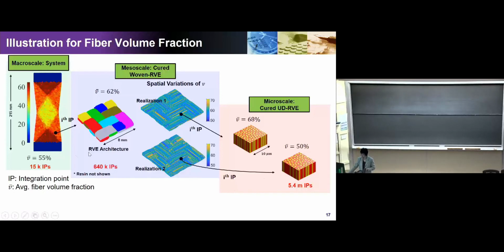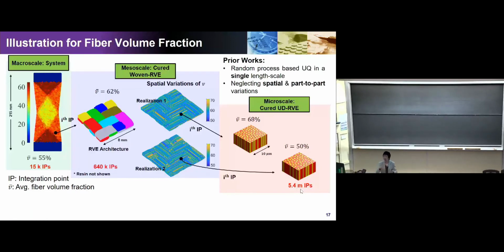So if you multiply, this is a nested situation, okay? So 15,000 times 640 K integration points gives 5.4 million integration points together. So it's a very large amount of work if you want to do all of them simultaneously using the original simulation code. In the prior work, we always saw people just treat them as a random variable, like volume fraction is a random variable. That doesn't really solve the problem, because if you're thinking about a random variable, everywhere it's the same for a particular sample, okay?